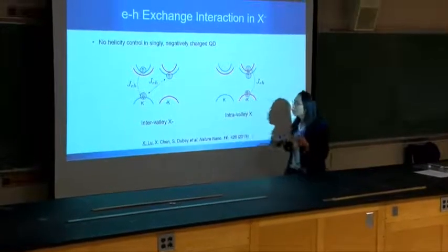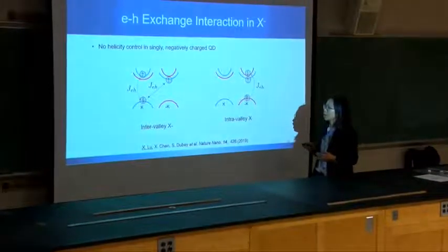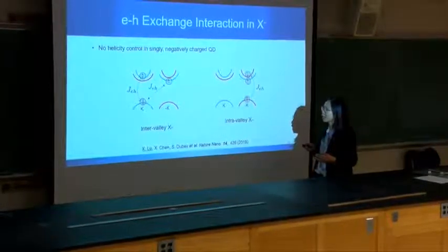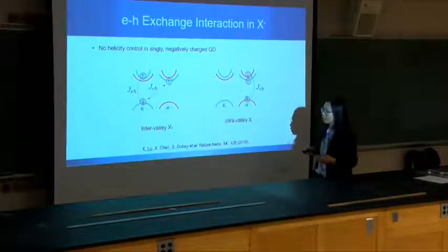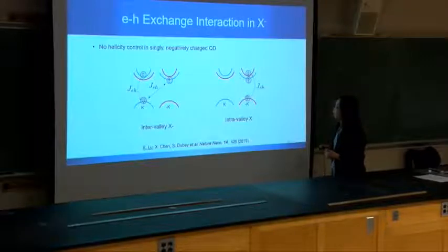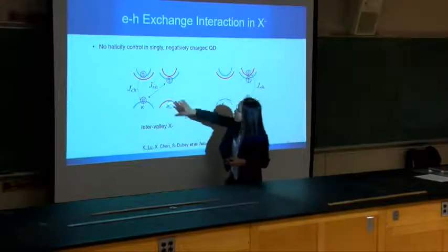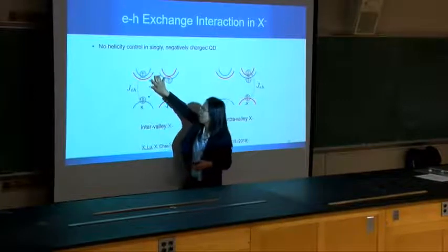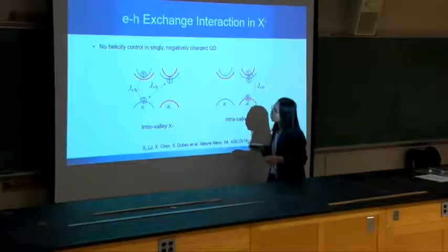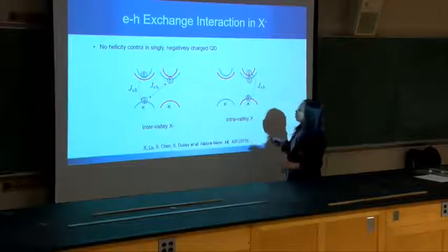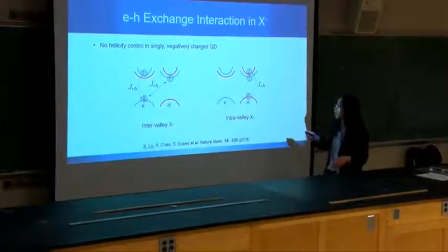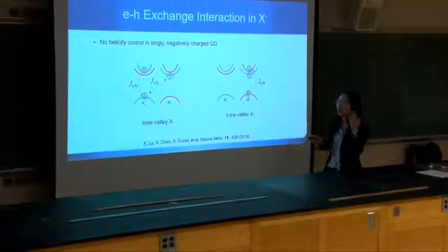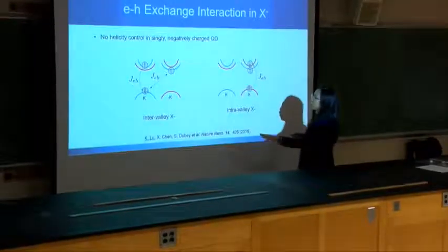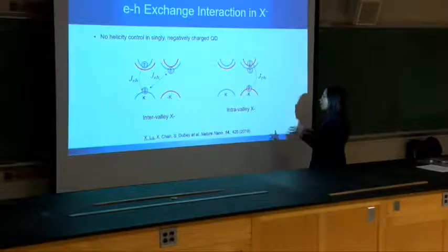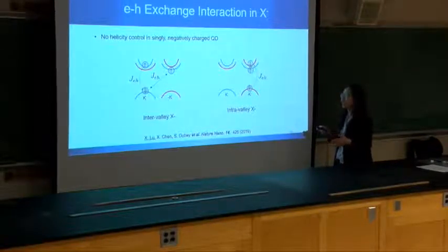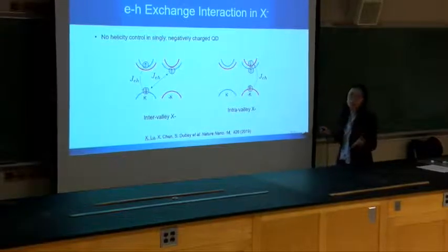It is a little bit more complicated here because, depending on where the actual electron sits, it can be either an intervalley trion or an intravalley trion. But in either case, as it doesn't form a singlet state, the electron-hole pair can still flip from the K valley to the minus K valley. So if we initialize the system in this left configuration, due to exchange it can flip to the right configuration, which means that one cannot have very good helicity control.